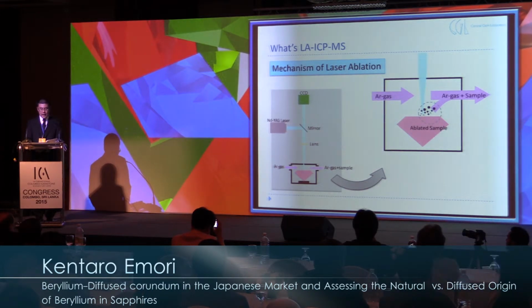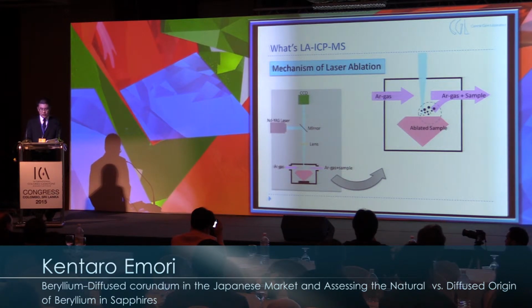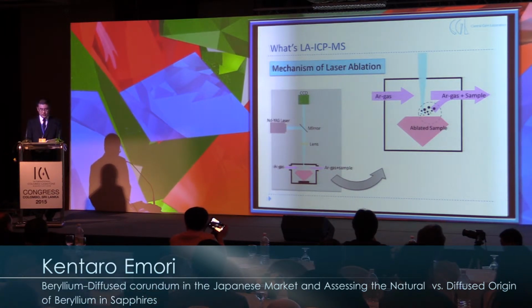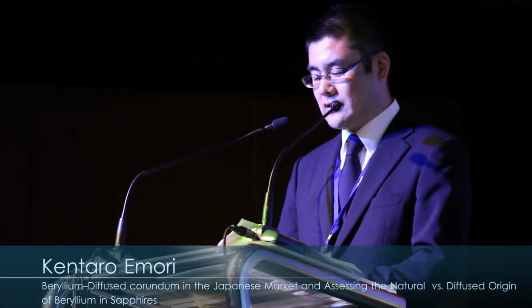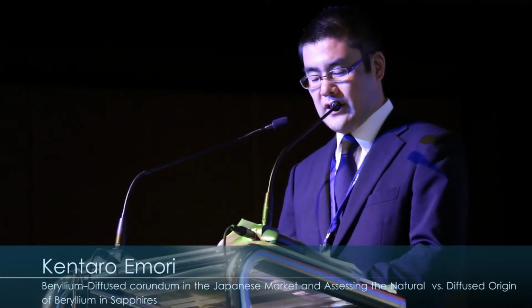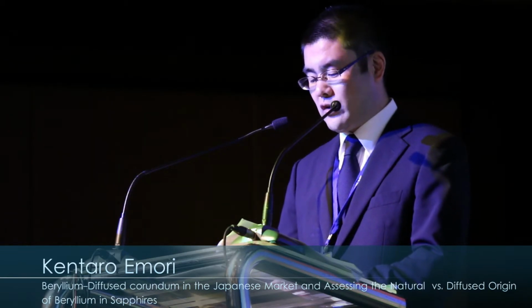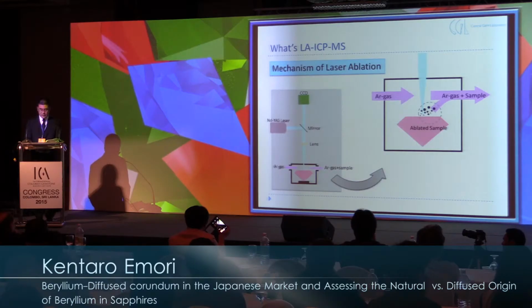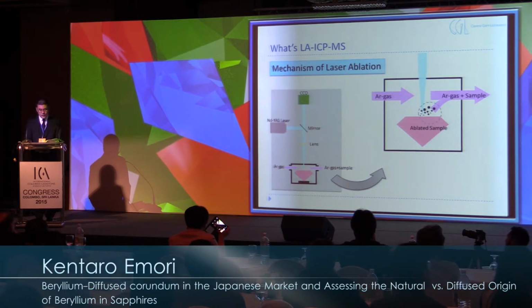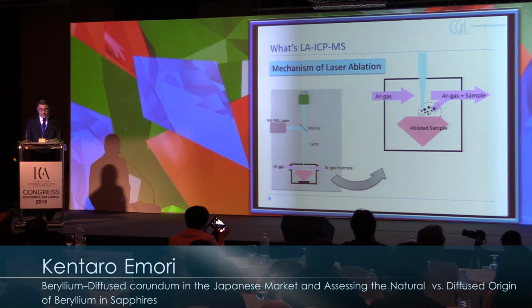At first, I explain the mechanism of laser ablation. The left figure shows a schematic drawing of the laser ablation system. This instrument includes a sample chamber, a Nd:YAG laser, and a CCD camera to monitor a sample. The right figure shows the sample chamber. When a sample is ablated by laser, a part of the surface melts and evaporates. Argon gas flow sends the evaporated sample to ICP-MS. This is the mechanism of laser ablation.